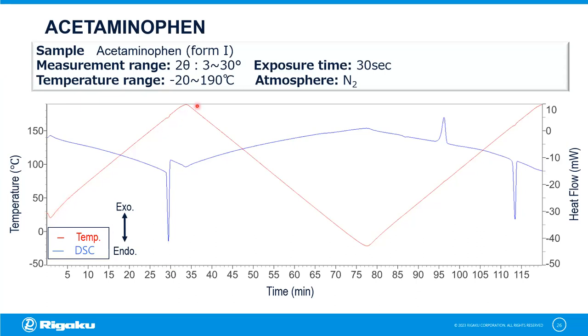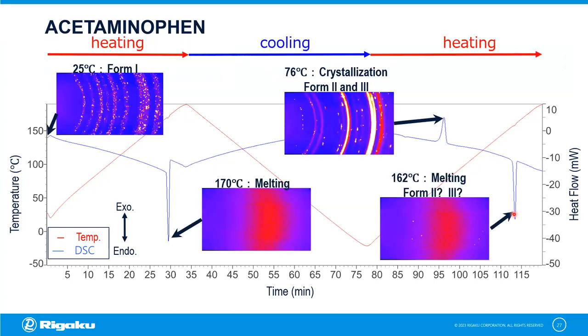The red line is the temperature as we move through this 2-hour experiment. X-axis here is time, y-axis is temperature. So at 170 degrees C here, we see that endotherm, the melting of the sample. We have then the amorphous stage. We see some small changes. As we drop the temperature, we get a crystallization. We raise the temperature and we get another melting of the sample.